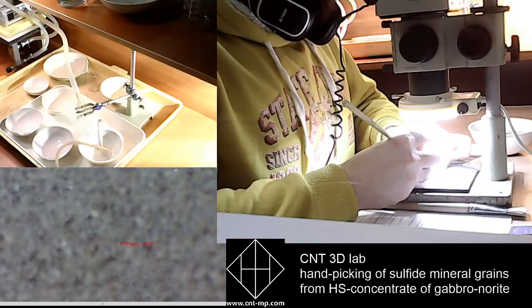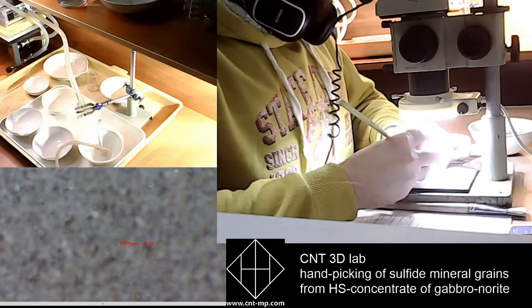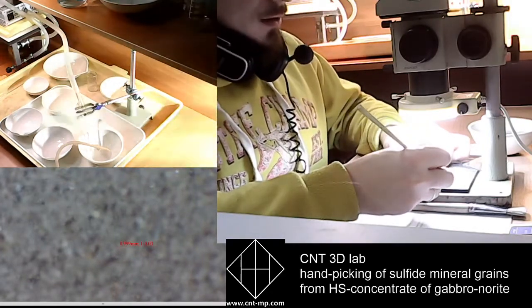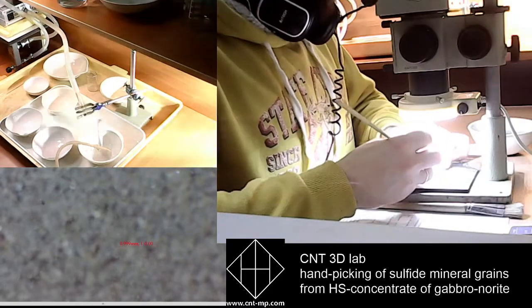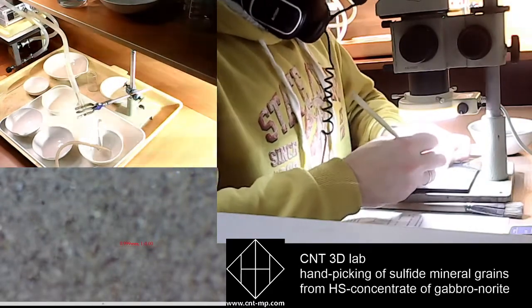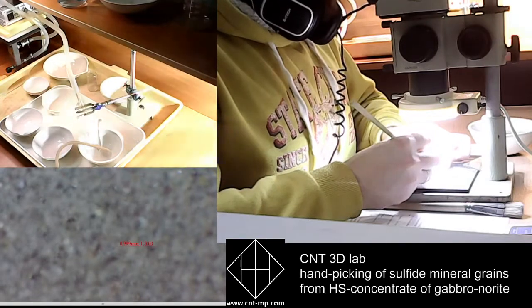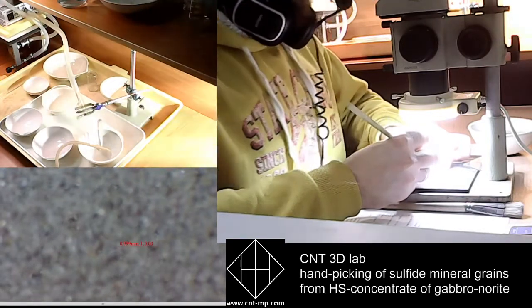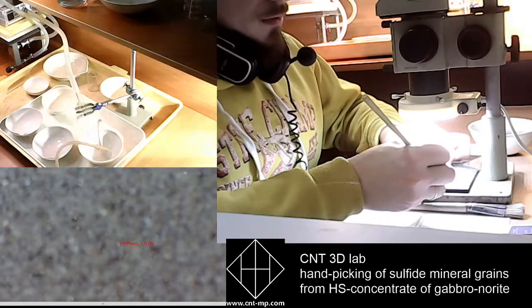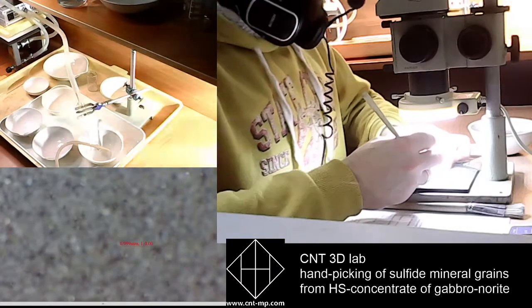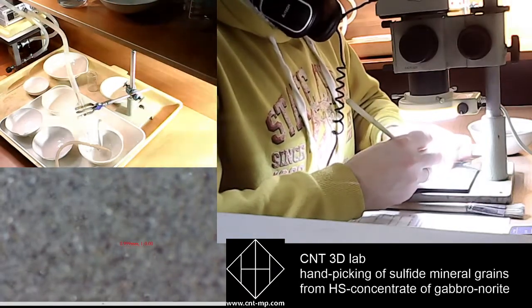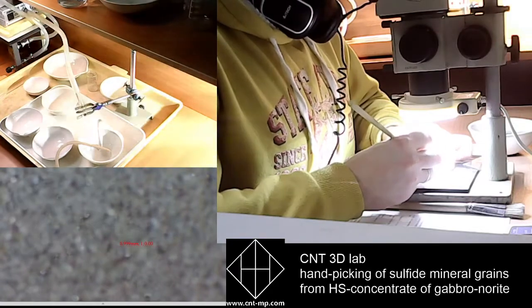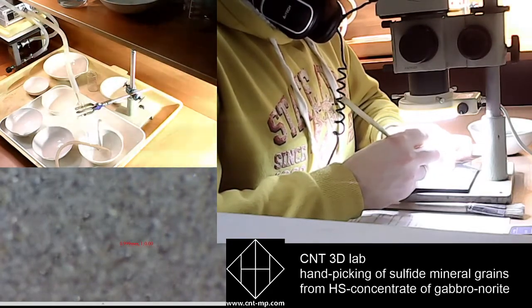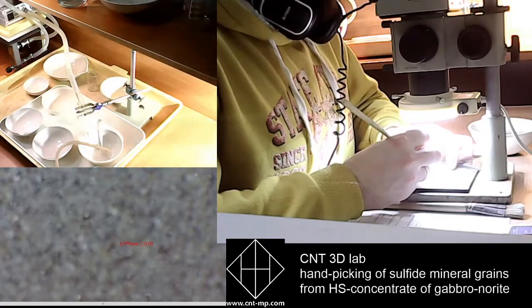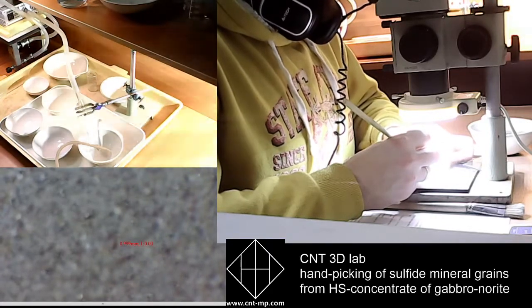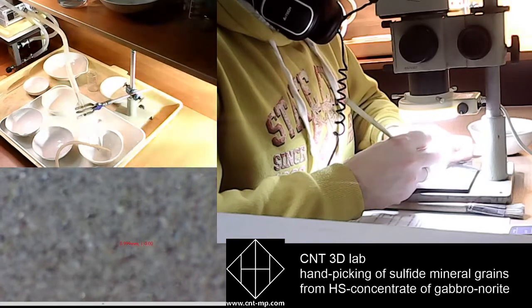There is a really small amount of sulfides in the source sample. By the whole chemistry, we know that the content of sulfur is about 0.05%, so it's about 200 grams per ton of sulfides.